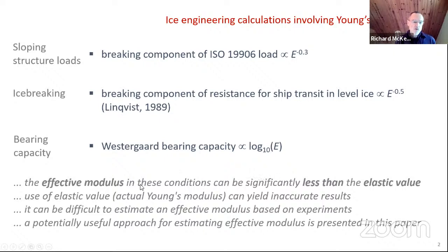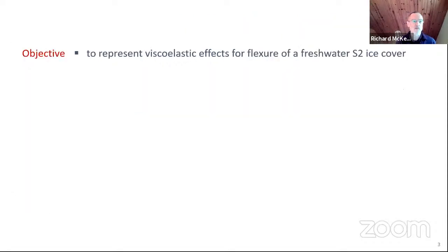And so the effective modulus in many practical problems in nature can be significantly less than the elastic value. There are a number of reasons for that, and I'll deal with them in the paper. But using the elastic value can yield inaccurate results, and it can often be difficult to estimate an effective modulus based on experiments. We've used a numerical approach to estimate effective modulus in this paper.